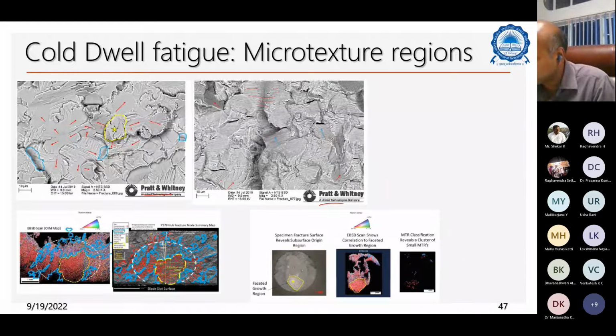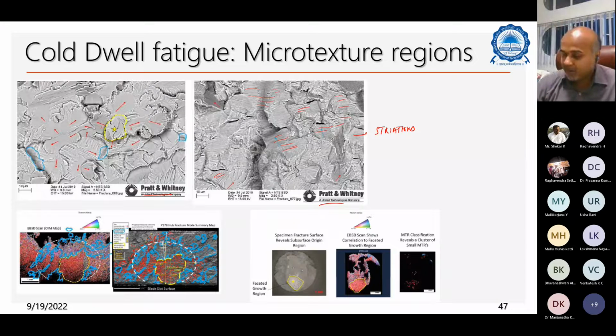Probably yesterday you would have seen a lot of images like this. These are the fatigue striations, sorry, striations. And then they figured out that they couldn't even notice it from this, so they used a technique called elemental mapping, which is used with EDS and EBSD, the electron backscatter diffraction spectroscopy. What they saw were very localized regions, called microtexture regions.